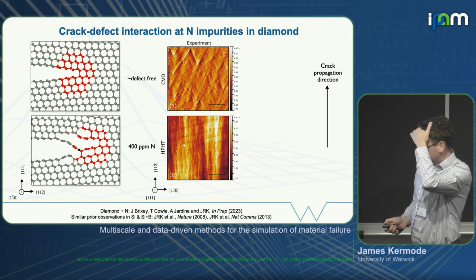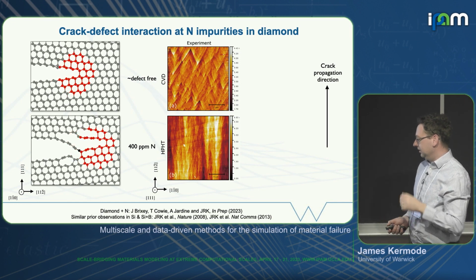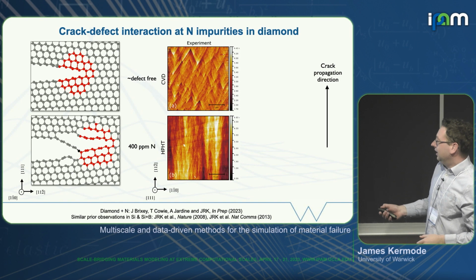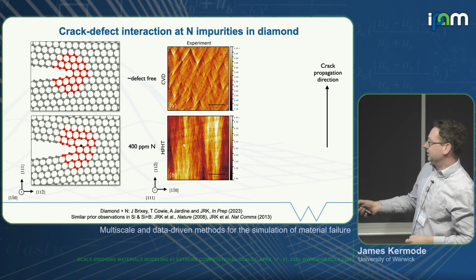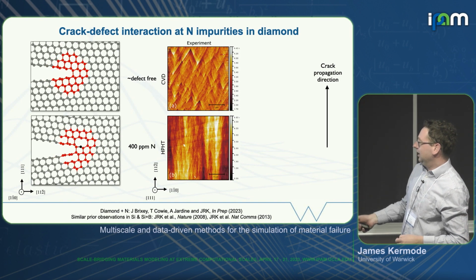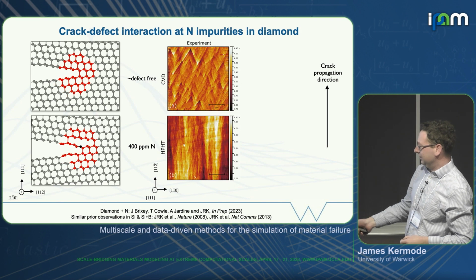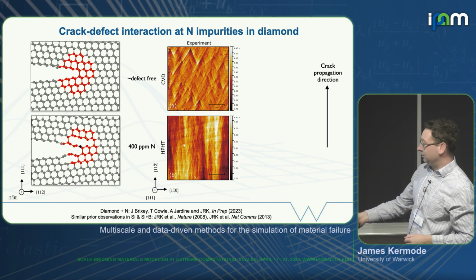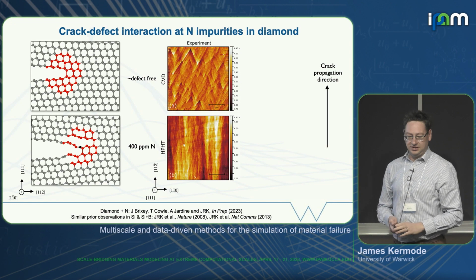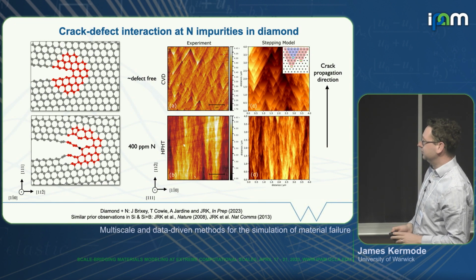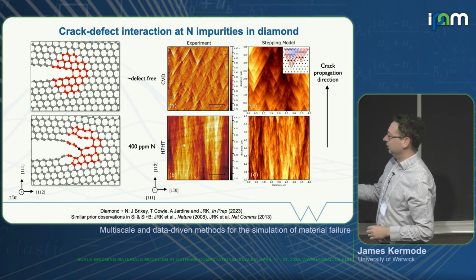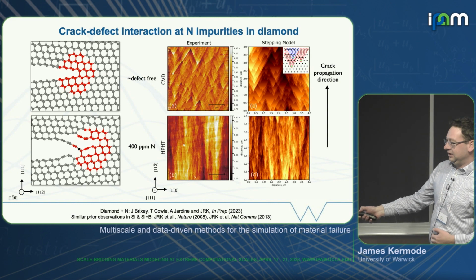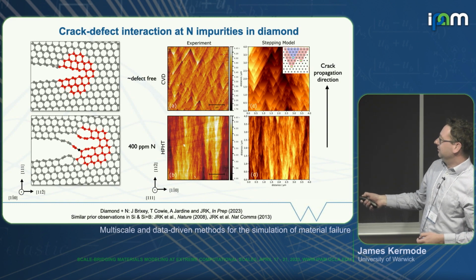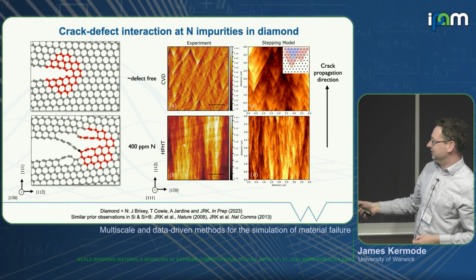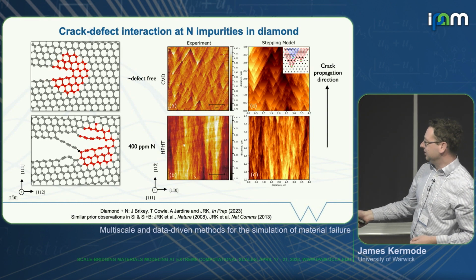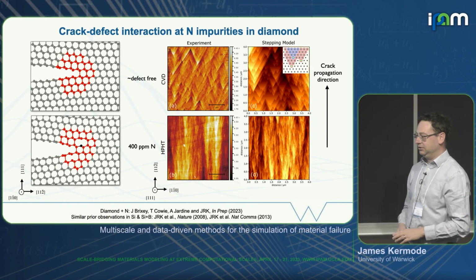So these are new experiments done by Andy Jardine in Cambridge. And we see if there aren't many defects around, you get a small number of these ridges. If you increase the concentration of defects, you get many more of these ridges, strongly suggesting that what we observe in the simulations explains the experimental surface response. We can go a bit further and build a simple model based on what we see in the QM/MM simulations, and we say that steps initiate at sites proportional to the concentration,